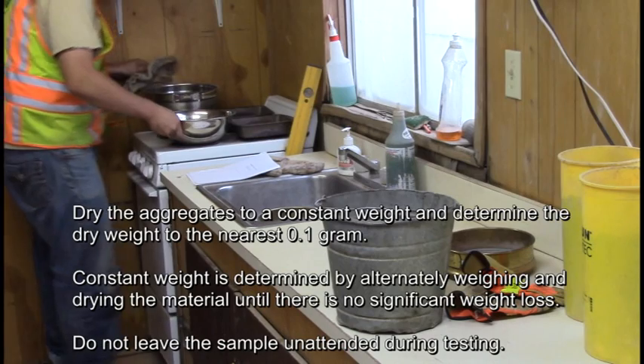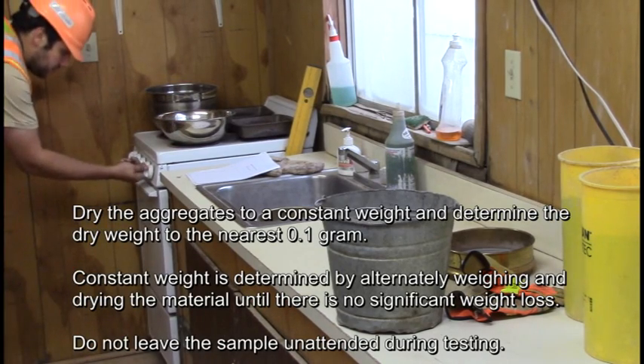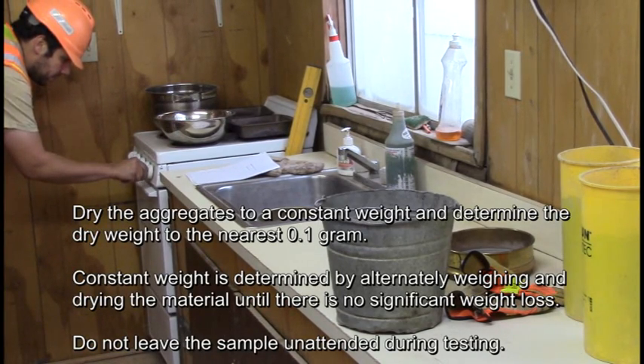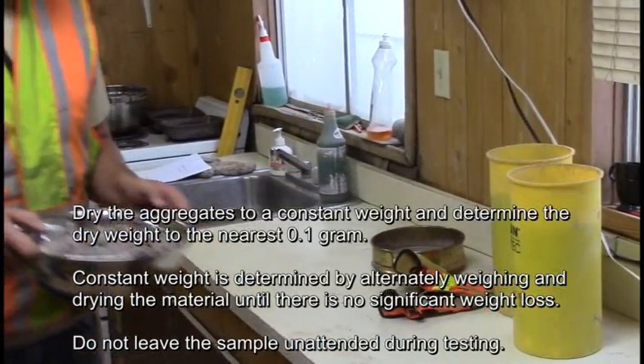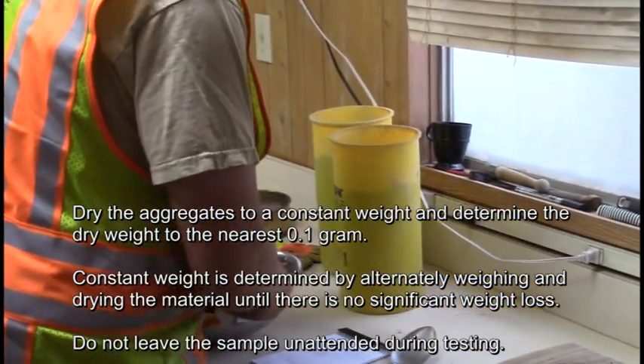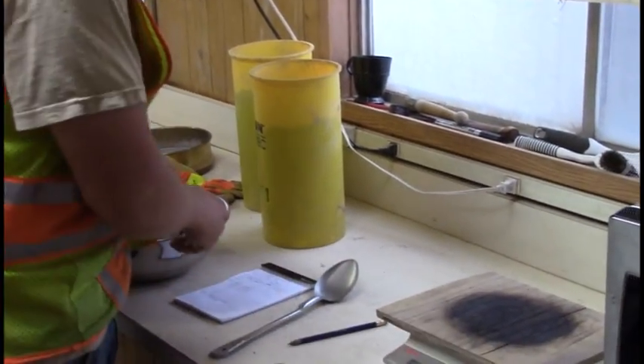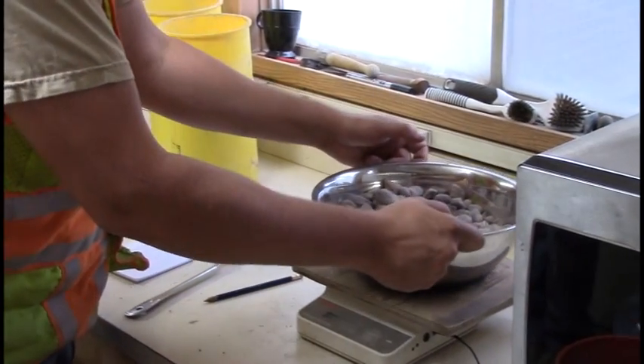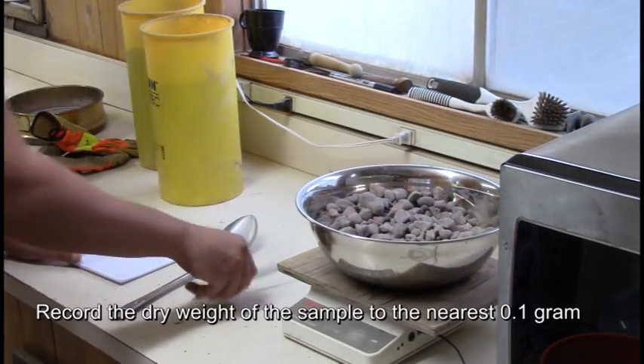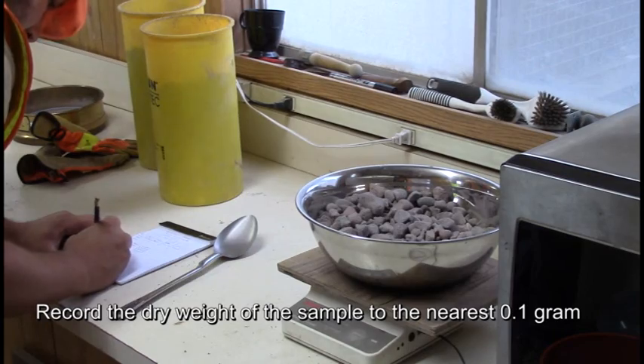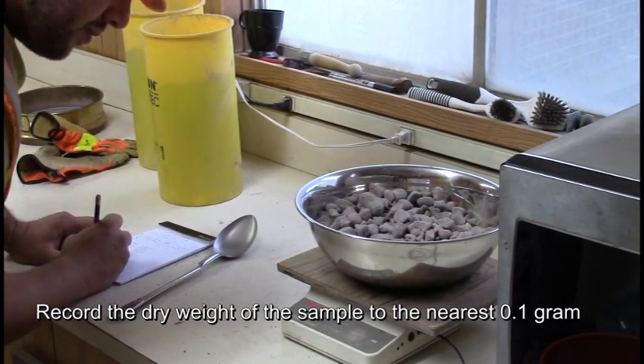Constant weight is determined by alternately weighing and drying the material until there is no significant weight loss. Do not leave the sample unattended during testing. Record the dry weight of the sample to the nearest 0.1 gram.